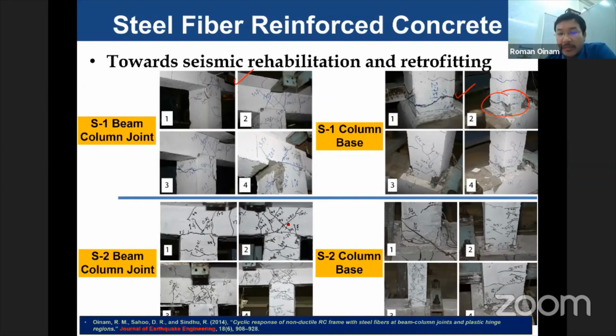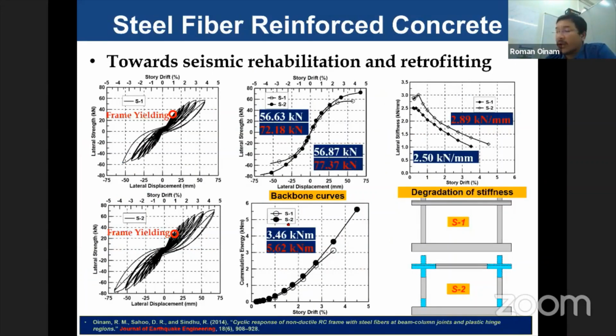Again, when we compare from the hysteresis point of view, this is the hysteresis response of the normal frame, and this is the hysteresis response of the SFRC. And in terms of the backbone performance, the steel fiber has slightly higher strength, but the ductility is better than the normal concrete.